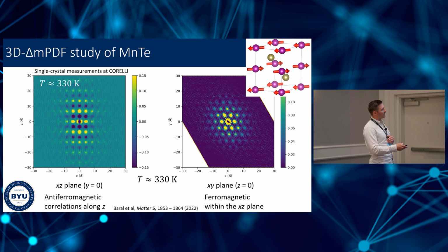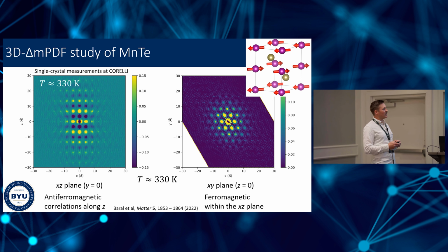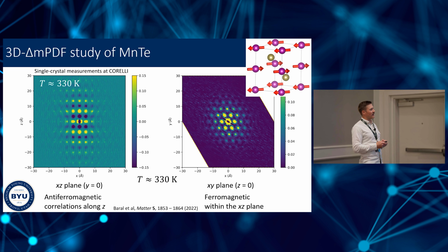And in fact, we can change our view and actually look at the 3D magnetic PDF in the plane, and we just have this nice hexagonal arrangement of bright spots, because within any given plane, the spins are all aligned with each other. So this is really neat. We can really view these local magnetic correlations directly in real space, even in 3 dimensions if we have a single crystal available.